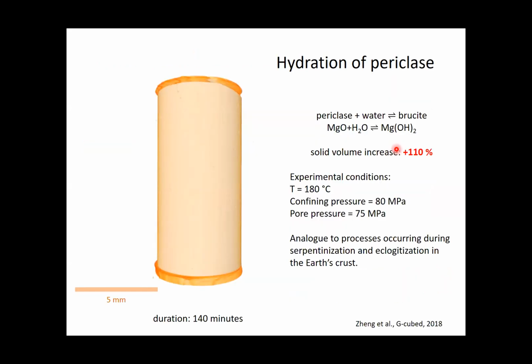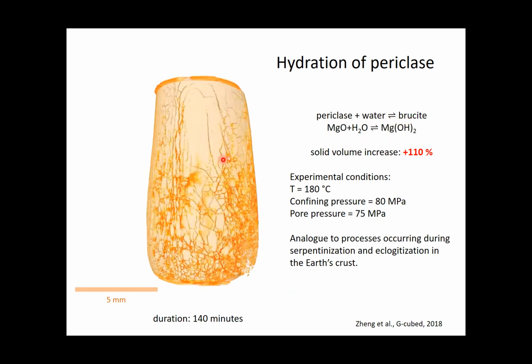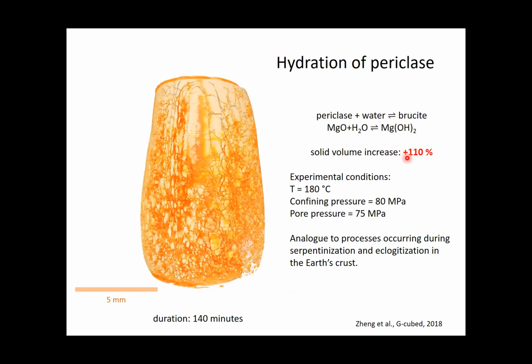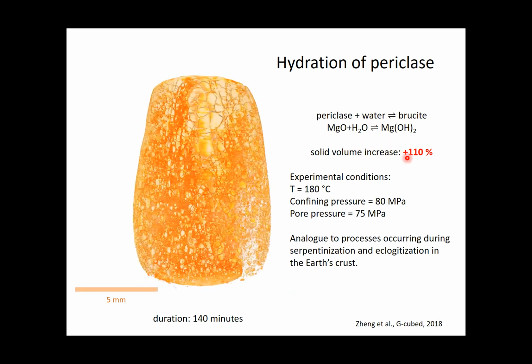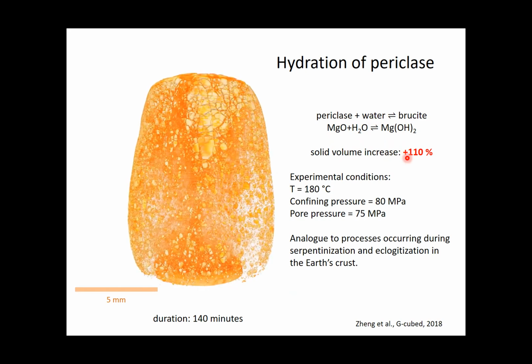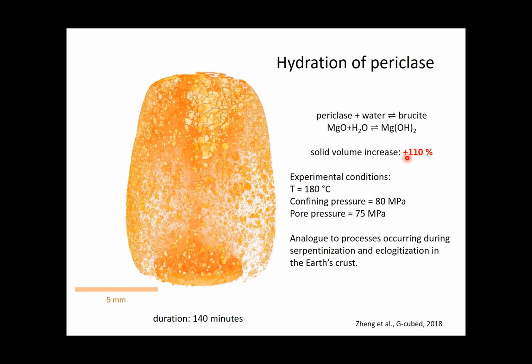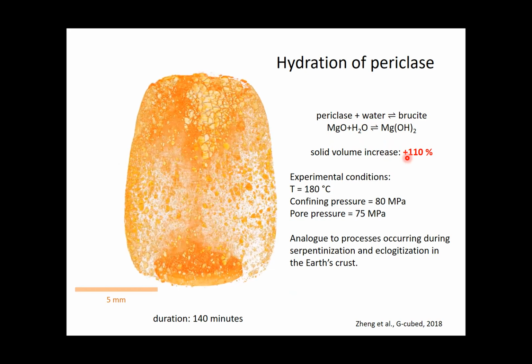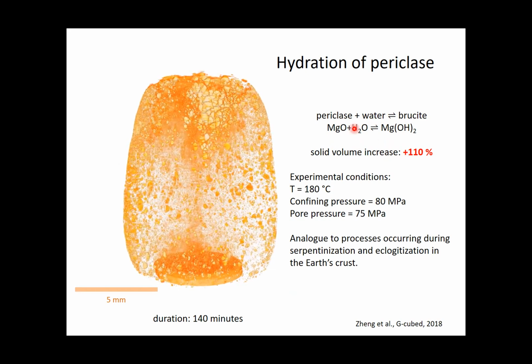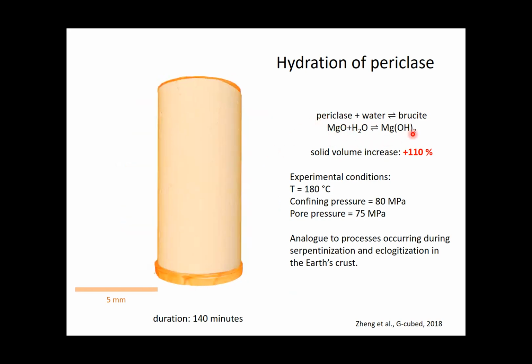So that's a movie of a piece of periclase, to which we add water. It evolves into brucite, and this reaction occurs with a solid volume increase of 110%. So a bit like liquid water to solid water, which occurs with a volume increase of a few percent. Here, the volume increase is much bigger. The initial MgO, which was orange, transformed into brucite, Mg(OH)2.